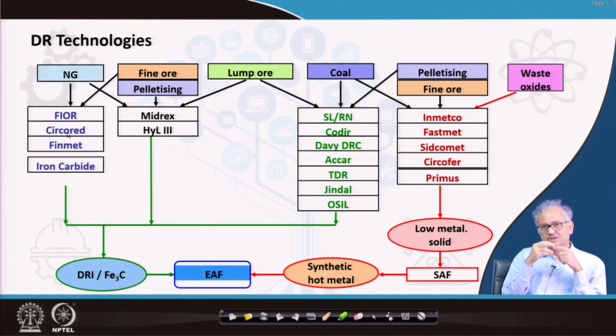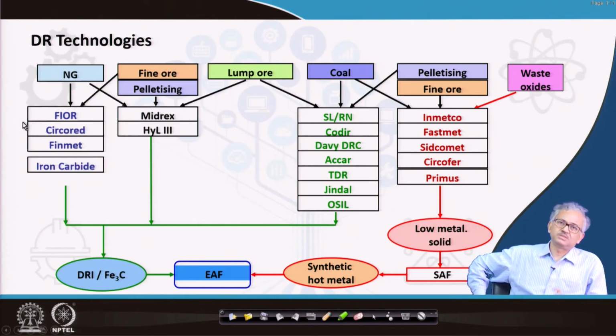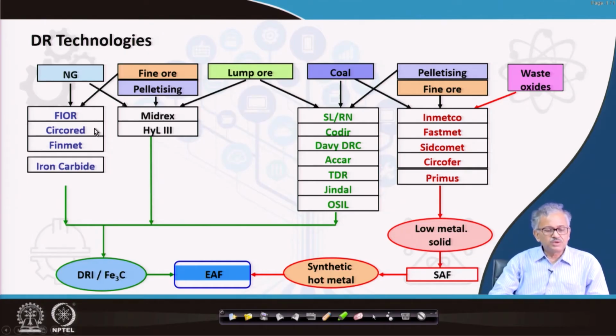in the fluidized bed process, the major problem is the sticking of the powders. When you are fluidizing this powder, after reduction, the powder has a propensity for sticking, because the powder contains a lot of gangue also, and the gangue material forms low melting eutectic, and then they try to stick to each other. So this sticking problem is there in the fluidized bed. That is one of the major problems. The powder tries to stick and agglomerate and then makes a process problem.